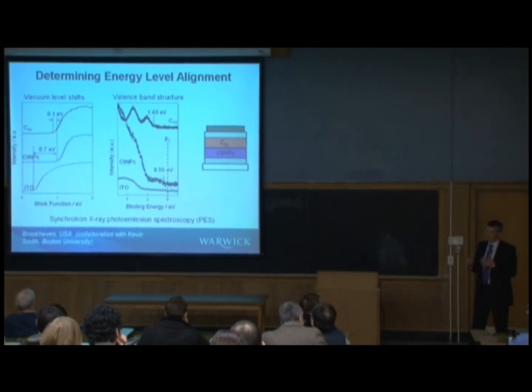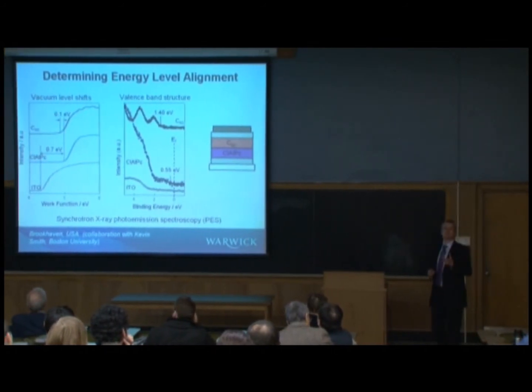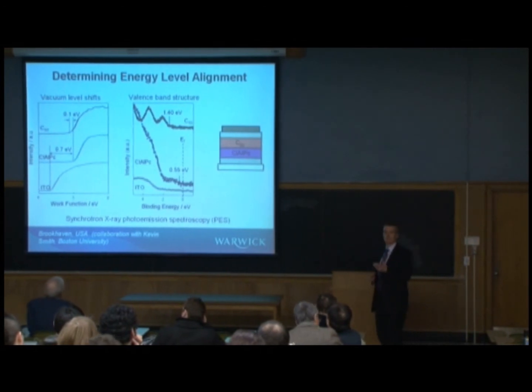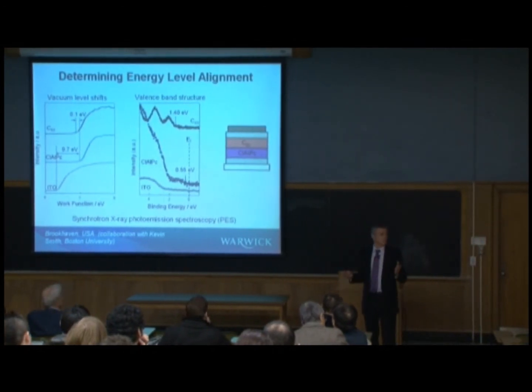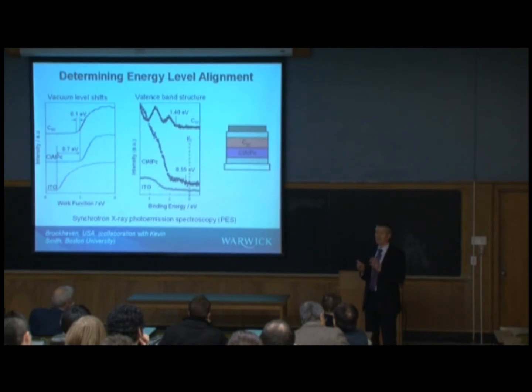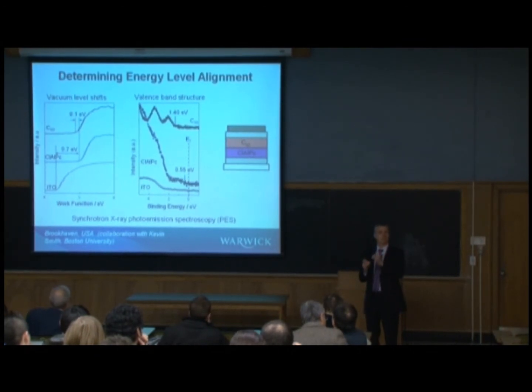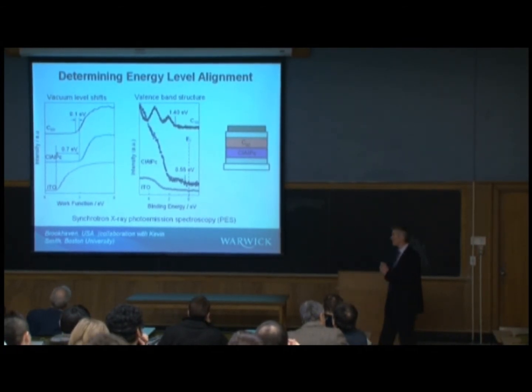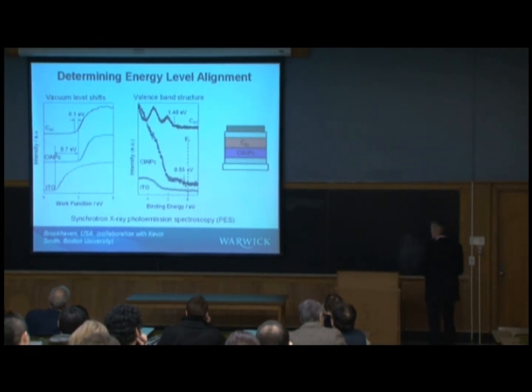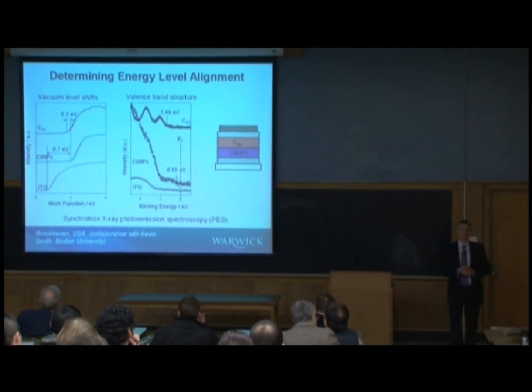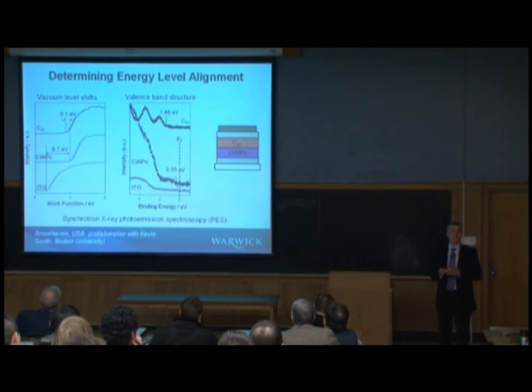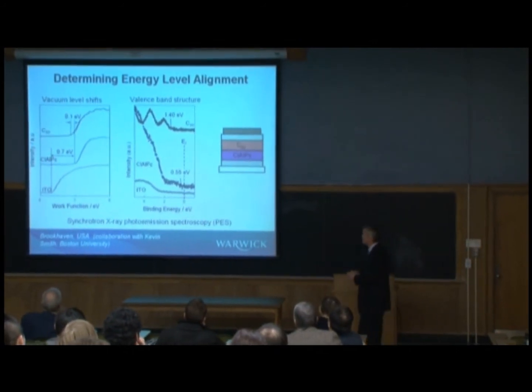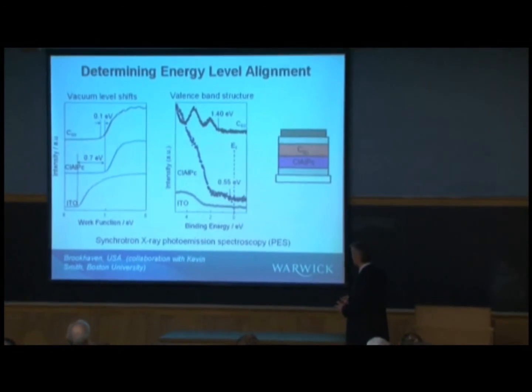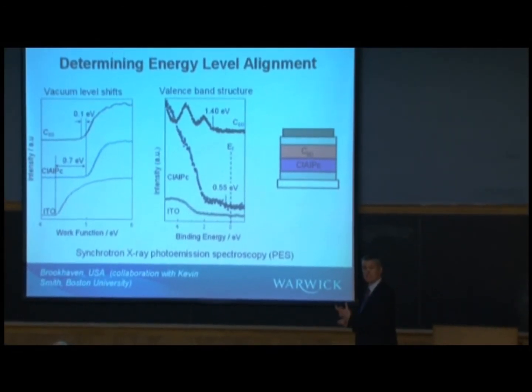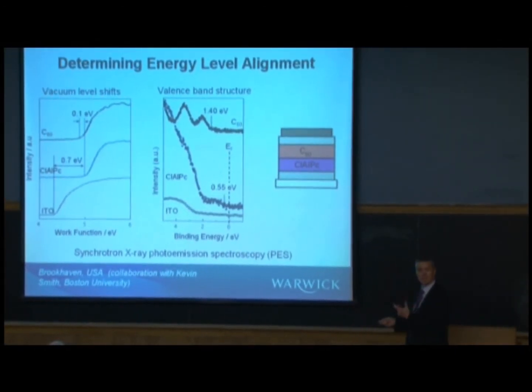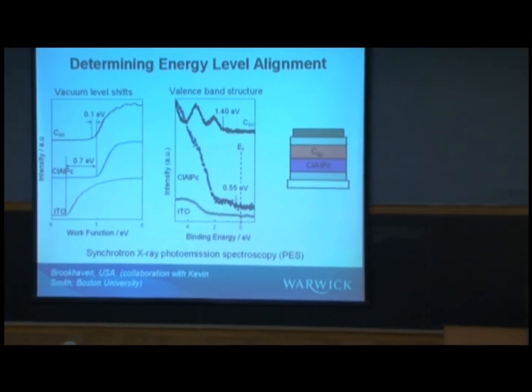In fact, if you read the literature, many of the numbers for energy levels and so forth that are bandied around are just blatantly wrong, actually. It's largely because there hasn't been that fundamental characterization to go hand in hand with the development of devices. So one of the things we've done quite extensively is photoemission spectroscopy, a very standard technique in inorganic semiconductors and other areas, to characterize the energy levels of these materials, to understand the interface gap energy, and then rationalize the open circuit voltage and hopefully maximize it.